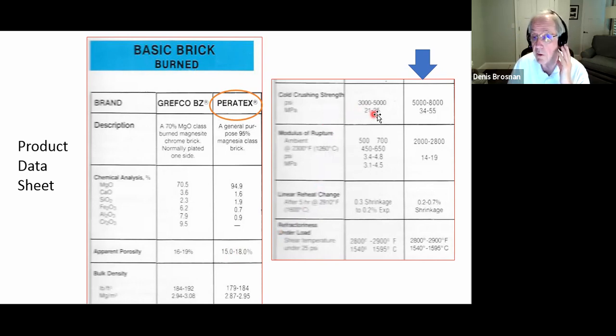There's compressive strength data for Peratex. Please ignore this column. It's for this other product, which we're not thinking about right now. There's a modulus of rupture. That's the strength in three-point bending. I'm going to talk about modulus of rupture in a minute, but it's just a strength value calculated as the maximum stress on the tensile side of the specimen at failure. Modulus just means typical. There's no particular significance to the use of the word modulus.